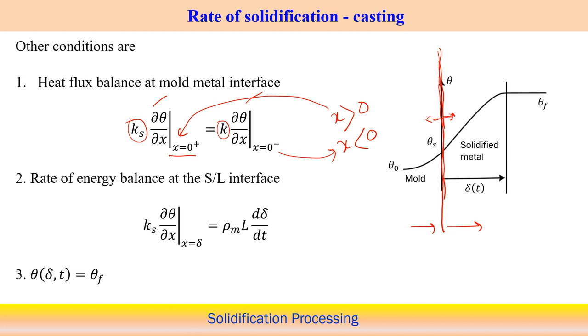The other is the rate of the energy balance at the solid liquid interface. So, we see the solid liquid interface means at the solid liquid, this is the liquid metal and this is the solidified metal. So, at the interface we can see the energy balance should also be maintained. So, that we can see what is the Ks, heat is conducted at x equal to delta, Ks delta T is basically the heat flux at x equal to delta.